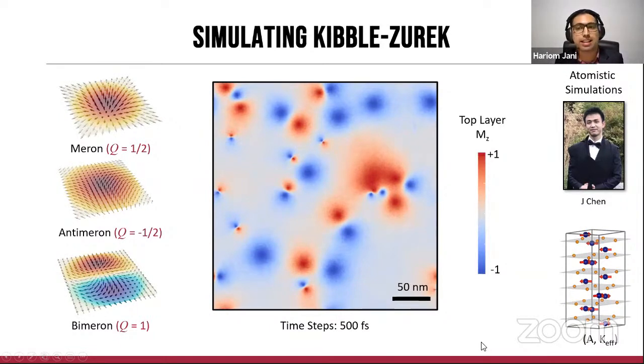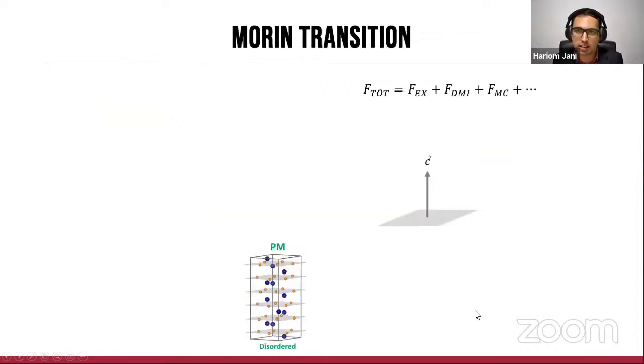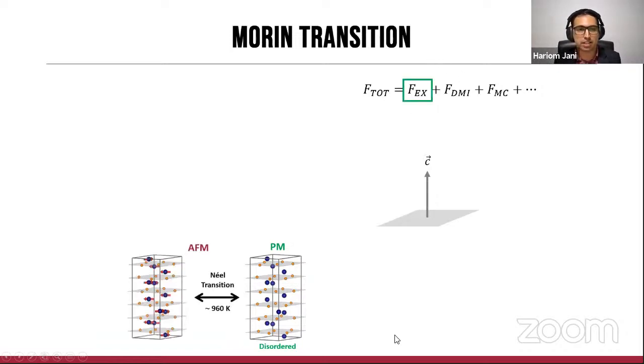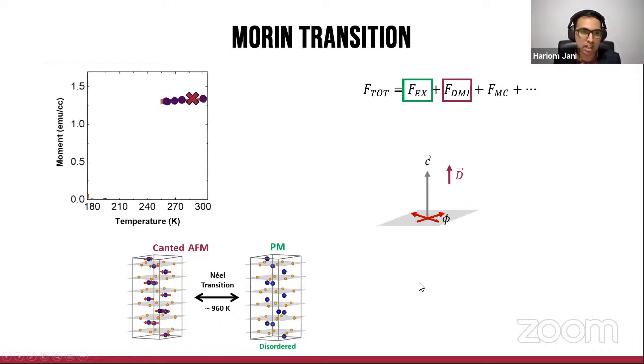So having convinced ourselves that it is possible to realize Kibble-Zurek transitions in a system with appropriately monitored A and K parameters, corresponding to exchange and anisotropy, let's look at what happens in the system and how we do it experimentally. The free energy of the system can be described by the following important terms. Firstly, the exchange, which guides the paramagnetic to antiferromagnetic phase transition. It has a very high Néel ordering temperature at about 960 Kelvin, which is extremely high, and it orders into the in-plane antiferromagnetic state. There is also a bulk homogeneous Dzyaloshinskii-Moriya interaction with a D vector out of plane, which causes an in-plane canting of the magnetization, which also ends up giving some kind of macroscopic moment that we can measure at room temperature.